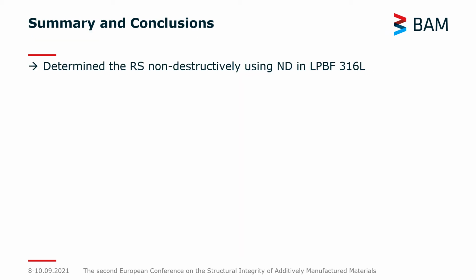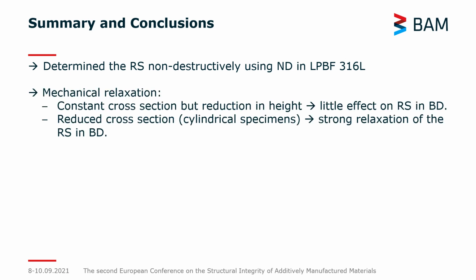Now, to summarize and conclude, we determined the residual stresses non-destructively using neutron diffraction in the laser powder bed fused 316L specimens. We looked at the mechanical relaxation starting from the as-built prism to the final testing geometry. Thereby we observed that when we keep a constant cross-section but we reduce the height of the specimen, we have a very little effect on the residual stresses in the build direction. If we reduce the cross-section, especially if we go towards cylindrical specimens, there's a very strong relaxation of the residual stress in the build direction.